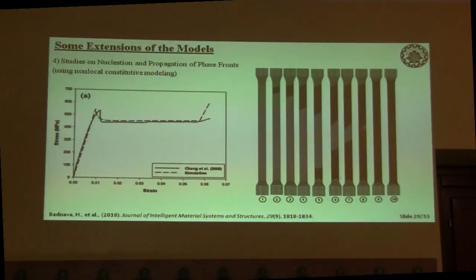We have observed some local deformations in SMA specimens. You can see here that transformation starts very close to one of the grippers in our experimental setup, and propagation of the phase front, initiation of a second phase front, can be seen in the results. Macroscopically, we can see some stress drop when localization occurs, and we have used non-local constitutive modeling to predict such behaviors.